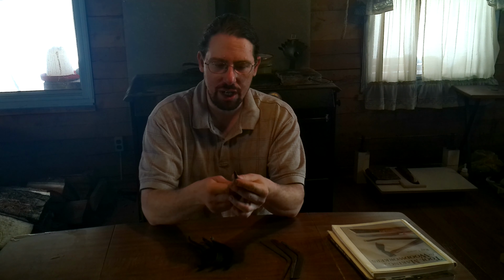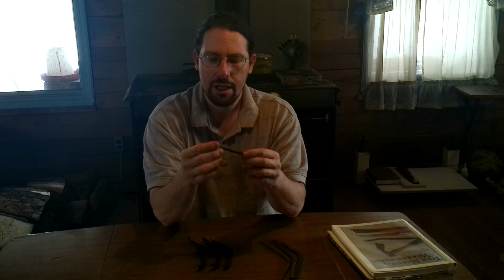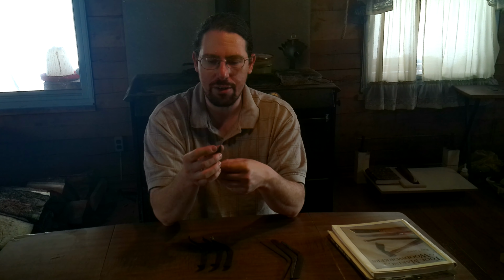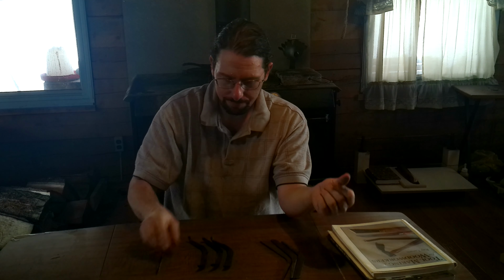Now, a graving tool or a scribe, this is a little triangle scribe that I want to stay very, very hard. So I only heated this one to 440 and then held it there for an hour in a kitchen oven. You can use a kitchen oven as a tempering oven. You don't need to go outside of the range of kitchen oven temperatures to do this. And that's kind of in the middle of the hard scribe range. Okay, so this retained most of its hardness.